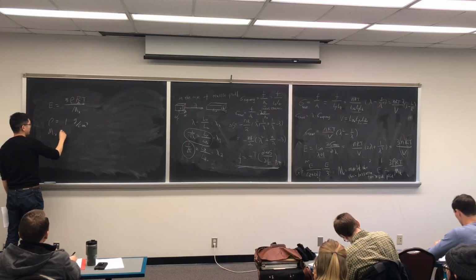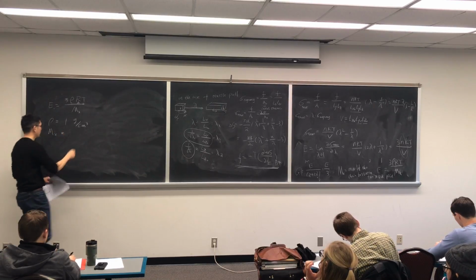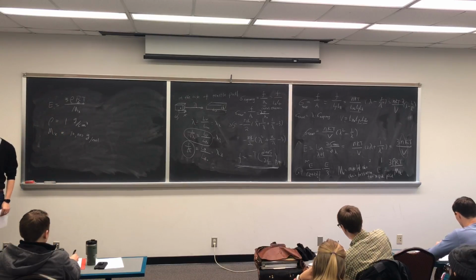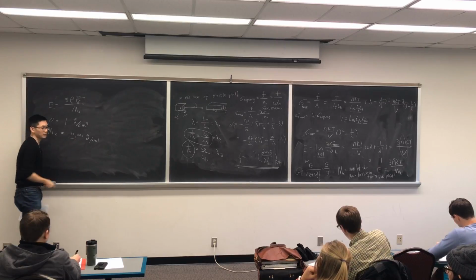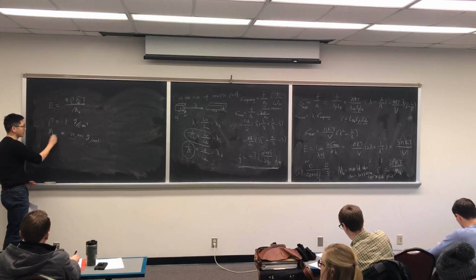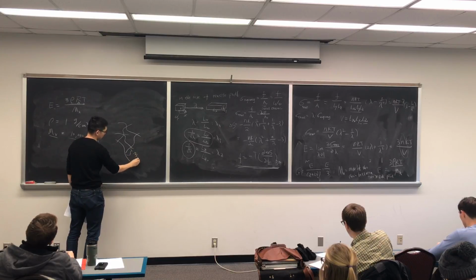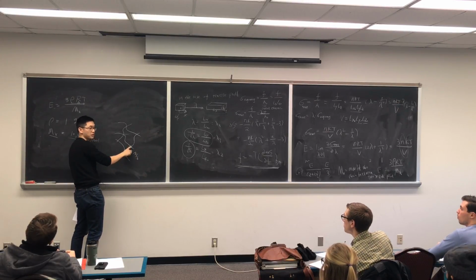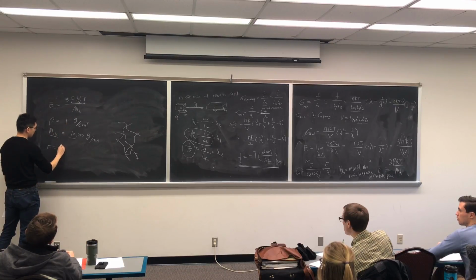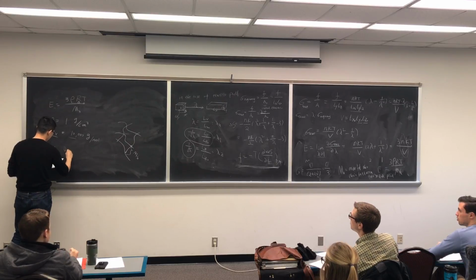And you know what R is, you know what temperature is, and actually you can just say a typical rubbery material has probably this much molecular weight between the cross-link points. And you can see this is about 10K, so relatively high. So these rubbery materials usually have a pretty good molecular weight, okay? So Mx means, now I'm going to draw a simplified model. That is the Mx, the molecular weight between two cross-link points for this material, okay? And you can calculate E from this equation, right? So if you do the math correctly, you get about 0.25 megapascal.